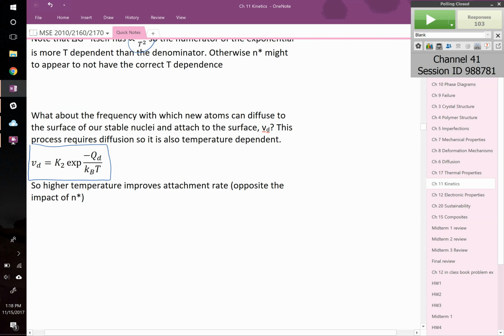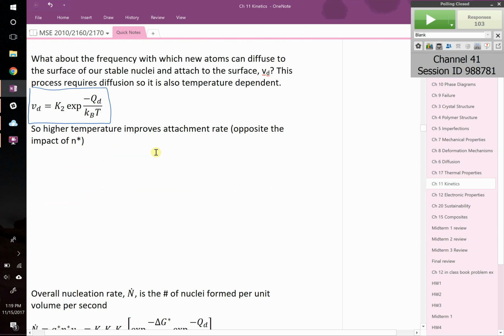V sub D equals K2, some other constant, times the exponential of negative QD over kBT. And QD is our diffusion activation energy, right? The same QD that we had when we modeled how fast carbon moves through a steel lattice, all those different things. You can look up what that activation energy is for your system, and that's how you're going to model growth, right? So with that said, you've got two factors: nucleation and growth. We need to take them both into account. So we do so as a function of temperature in a graphical way like this.